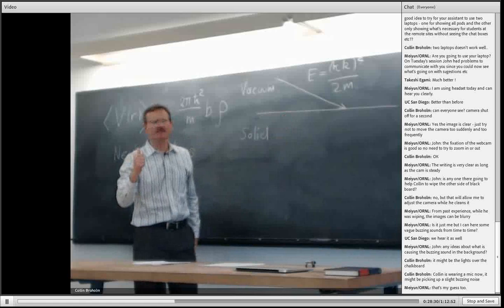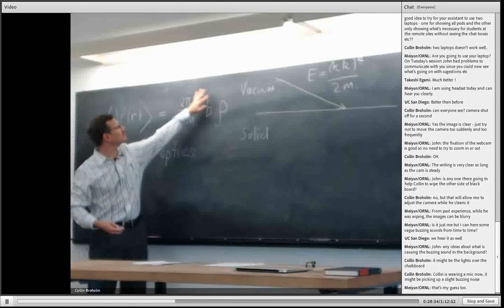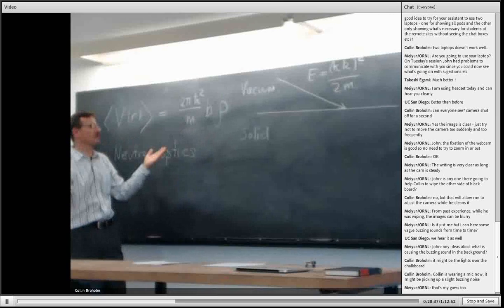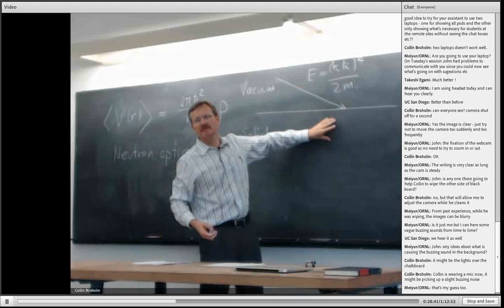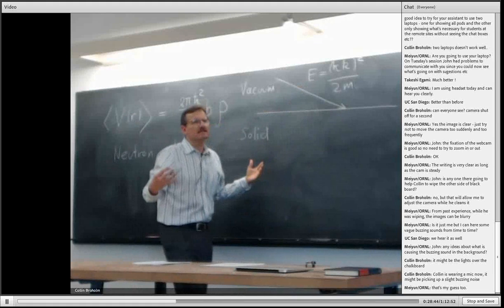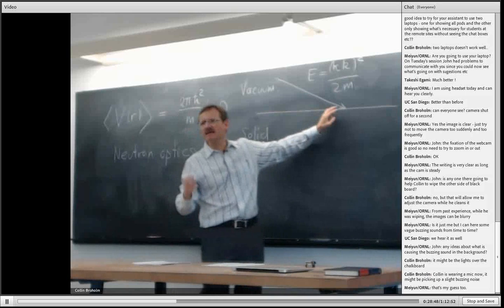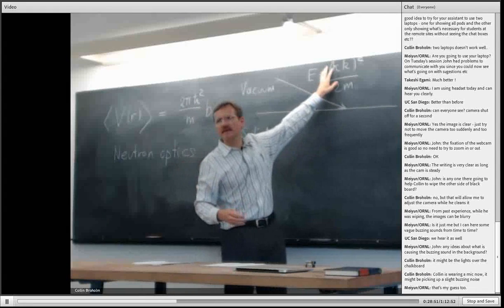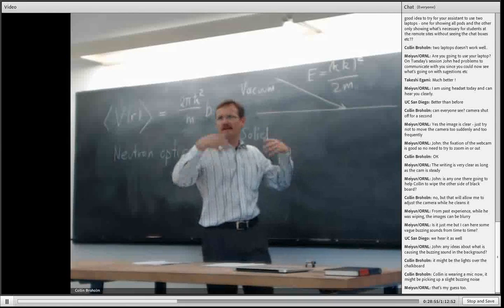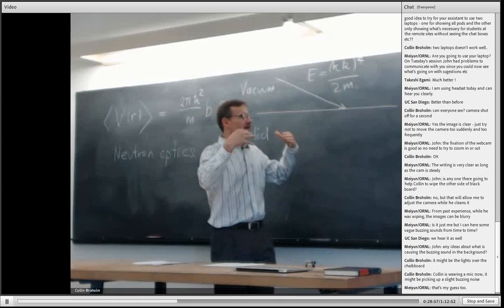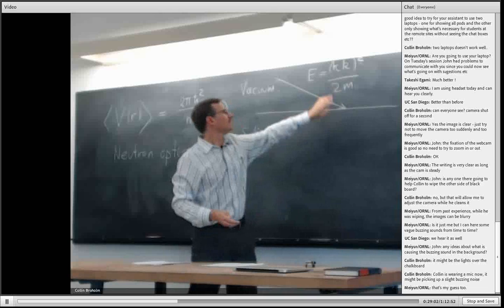Now inside the solid, the potential energy has actually increased, we claim, according to this smeared Fermi pseudo-potential. However, the energy cannot change as I pass through this interface. It's an elastic process. If you want to think about it from an electromagnetics perspective, then you won't be able to satisfy the boundary conditions if you were to change the energy from this side to that side. The wave function has this time phase factor in it, and the boundary condition has to be satisfied at all times. So I really need the energy to be the same across this interface.